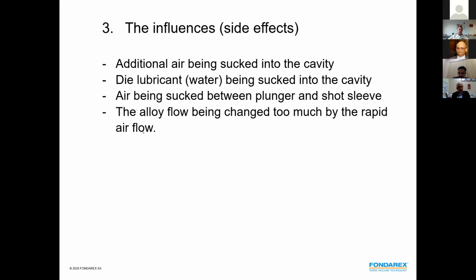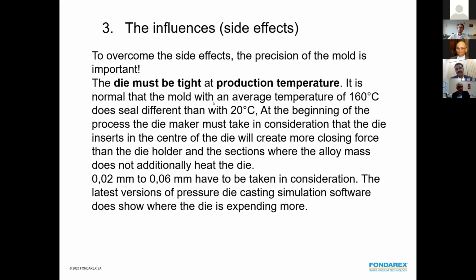And another big task is that the alloy flow in the runner, from shot sleeve to runner, in the runner, sometimes even in the cavity, is getting slightly different under the use of vacuum. And therefore we also have to find a good way of how much vacuum in which sector we need to have an optimum airflow inside.